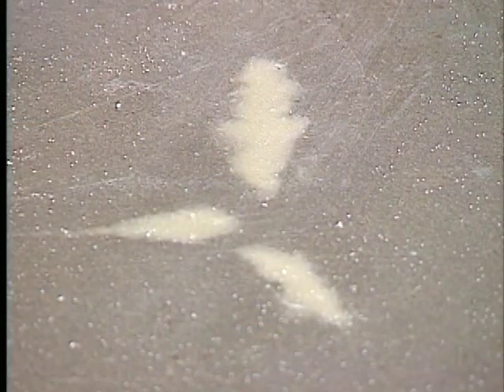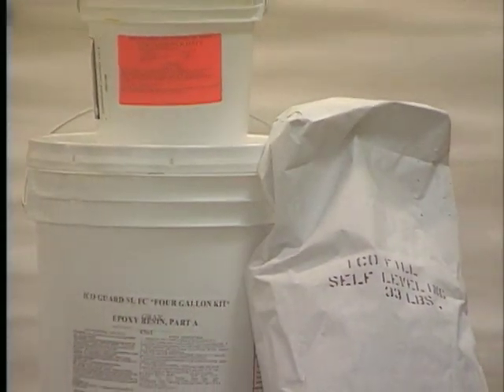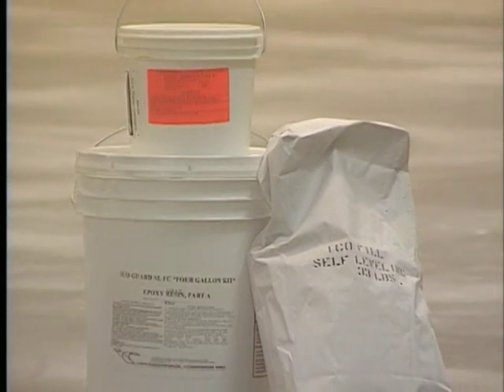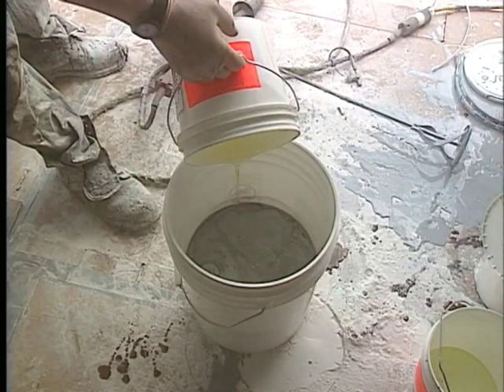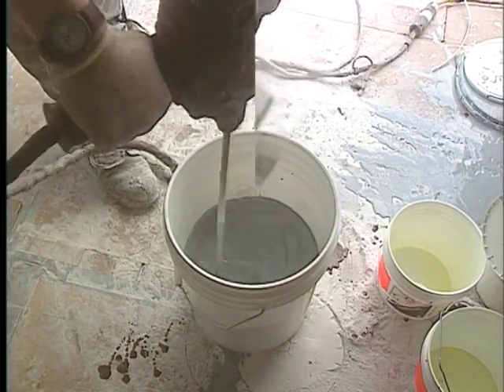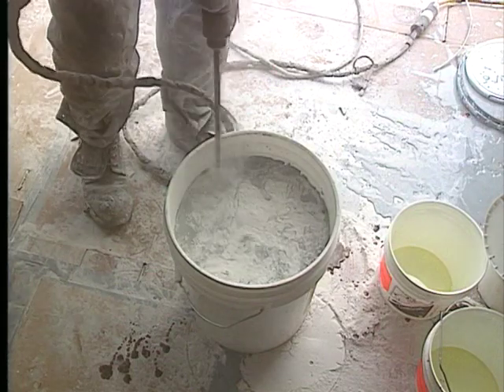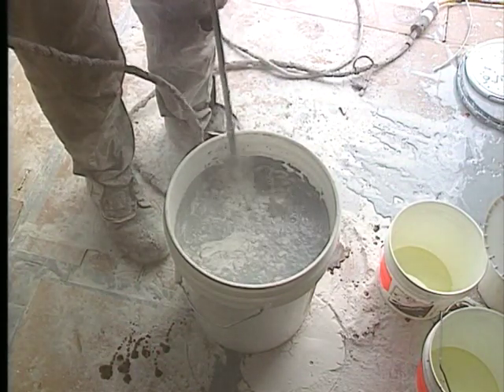For surfaces such as these, the first step is to use ICO primer to seal the surface and reduce chances for outgassing, which can produce pinholes in the finish. ICO self-leveling material comes in pre-measured 4-gallon kits. Mix part A and B with a Jiffy-style mixer, add self-leveling filler, and then mix for 1 to 2 minutes at low to medium speed.